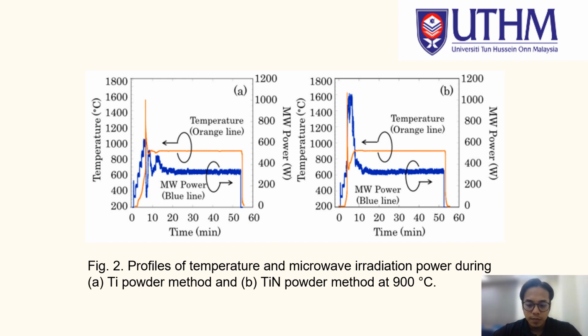In figure 2, after the temperature reached about 500 Celsius, it immediately rose above 1500 Celsius in both cases. This rapid temperature change was also seen at the other temperature conditions of 800 and 1000 Celsius. This behavior seems to be thermal runaway. Figure 2 indicates that the temperature change of the upper parts and the sample behave similarly in both cases. However, the inner temperature of the titanium nitride powder seems to be lower than that of the titanium powder. It is difficult to measure the inner temperature, but SEM images can give some indications, as discussed later in this section.